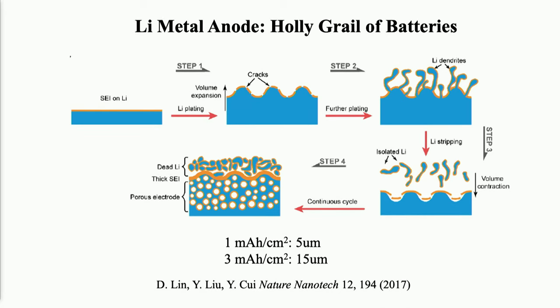During plating and stripping, when you charge your battery, you're going to plate lithium, it becomes thicker and thicker. Because it's a plating process, it's metallic, you form this dendritic structure. You lose control.